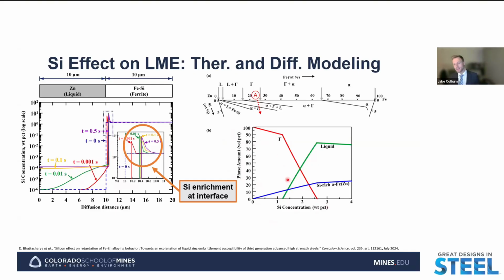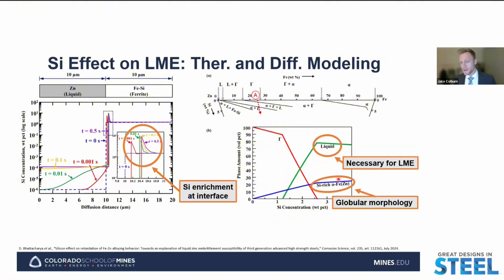And what we see is that as the silicon concentration increases at the interface, we have a decrease in the equilibrium phase fraction of the gamma phase, and then an increase in the equilibrium phase fractions of the liquid and the alpha iron zinc phases. And so that's important because if we're increasing the phase fraction, if we're further stabilizing the liquid phase, that is going to be detrimental to LME susceptibility because this is the phase that is necessary to initiate and propagate LME.